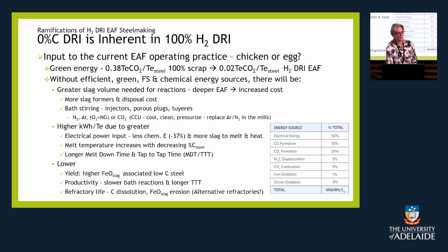And the melt temperature actually increases with the lower carbon in the steel. There's also going to be a much longer meltdown time and tap-to-tap time, which is going to lower your yield, and that's a big financial incentive, to increase your yield and throughput productivity.